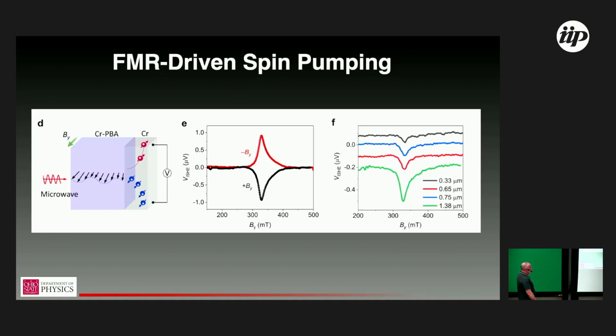You can then use that very sharp resonance, or long-lived magnons, however you want to think about it, to explore interesting physics. The motivation for this paper was, I think, thermoelectric. They were looking at FMR-driven spin pumping, and I'll show thermal effects on the next slide. This is well-established spintronics at this point, where you excite your magnet out of equilibrium, creating a population of magnons that generate a chemical potential that drives spin into an adjacent layer, in this case chromium, acting as an inverse spin Hall detector. That spin current, in the presence of spin-orbit coupling, gives rise to a transverse voltage, which you can use to measure the presence of the FMR.